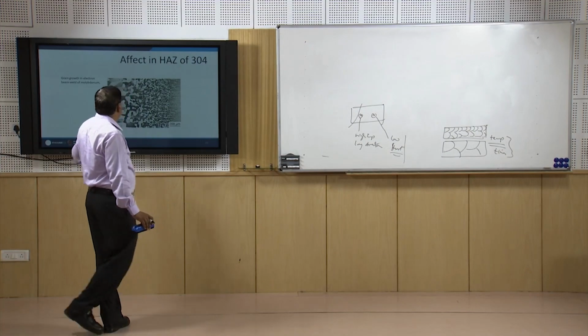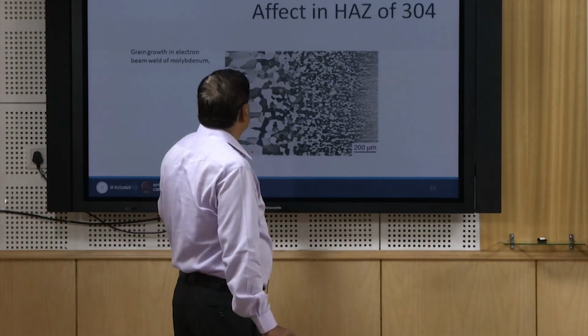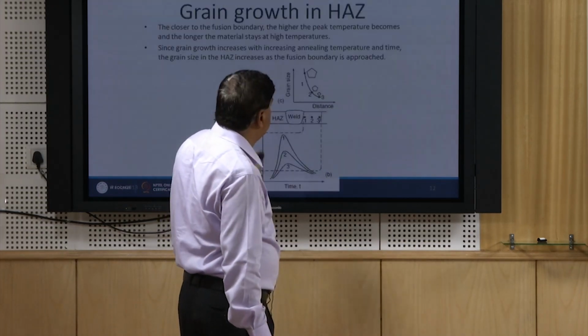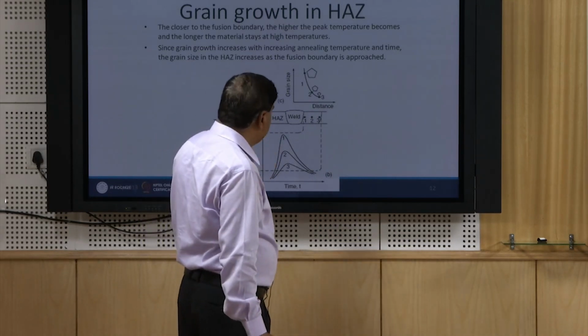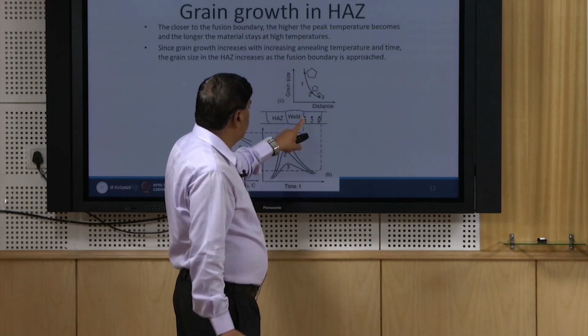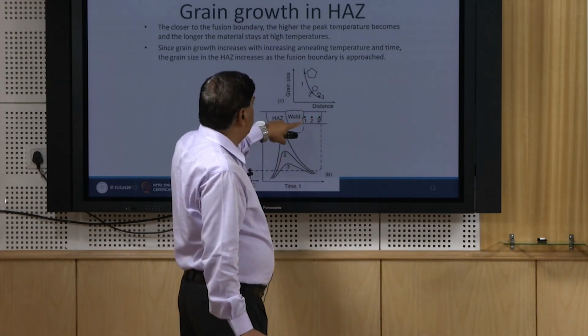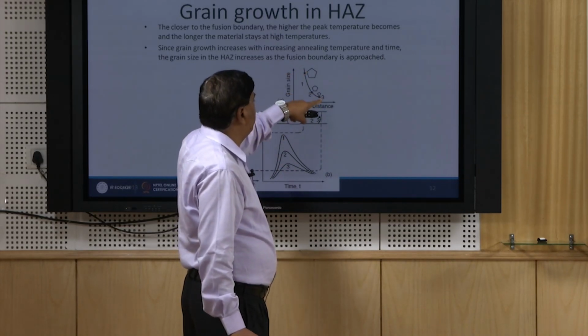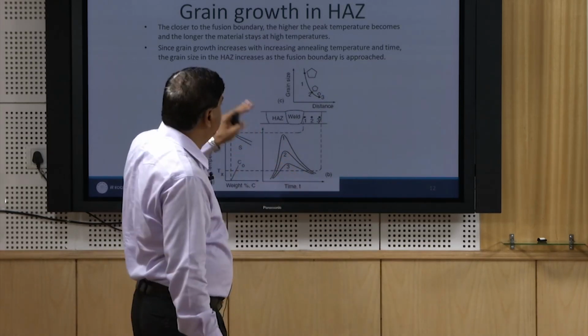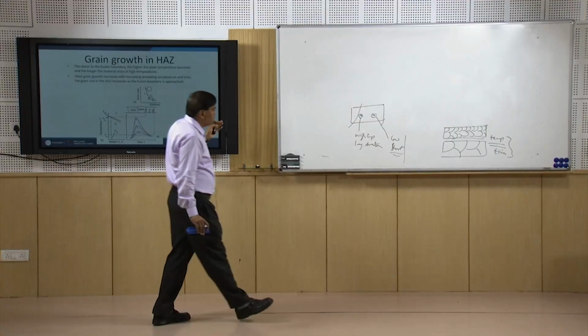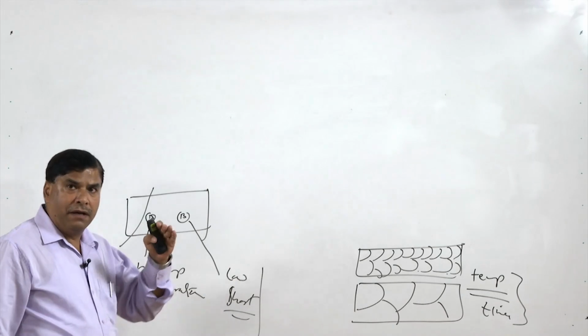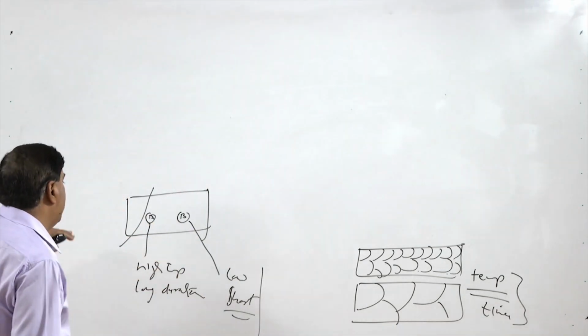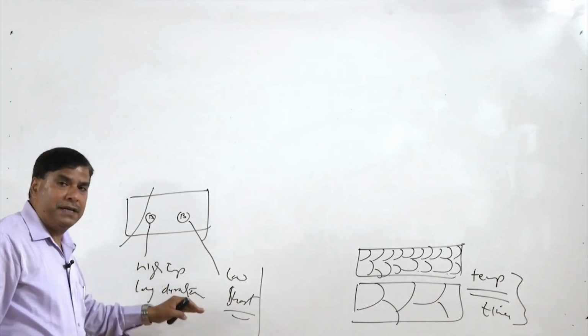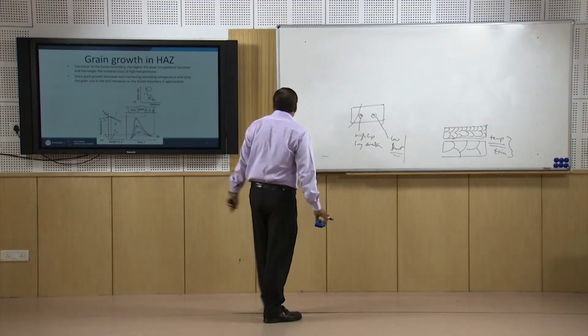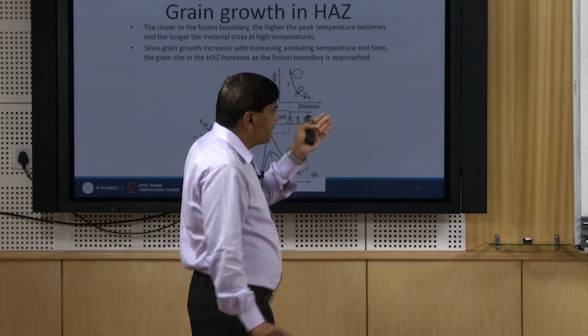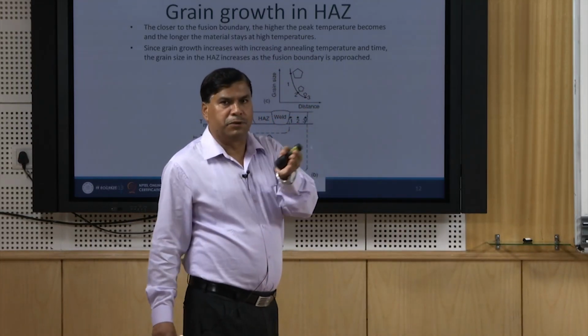This is what we can see here. The points which are very close to the fusion boundary will have coarser grains, and as we move away from the fusion boundary, the coarsening keeps on decreasing. The same thing can be seen from here: point 1 is very close to the fusion boundary as compared to points 2 and 3. So, point 1 will experience more grain growth as compared to points 2 and 3. Point 3 will have the minimum grain coarsening as compared to points 2 and 1, and the main reason for this is the difference in the peak temperature and the duration for which higher temperature exposure is given. The temperature will be higher, and it will be for longer periods for point A as compared to point B. So, that is why we see that the maximum coarsening takes place near the fusion boundary as compared to those away from the fusion boundary.